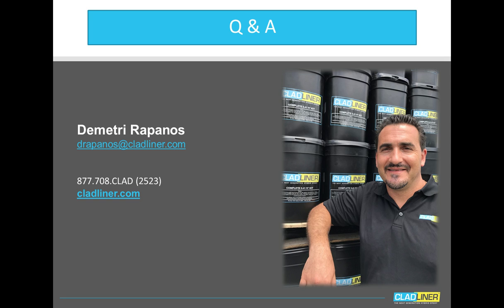What is the curing time for the product? You'd start feeling firmness, depending on the conditions, obviously. If we're talking about 75 to 80 degree ambient conditions, you'd start feeling firmness probably within about 2 hours. Full cure is probably about 18 to 24 hours. However, because it continues to cure in moist, wet, and humid environments, unless the manhole itself is extremely aggressive when it comes to water flow, the structure can be returned to service once that initial firmness to the touch is reached, and it can continue to cure with the lid on and back in service.